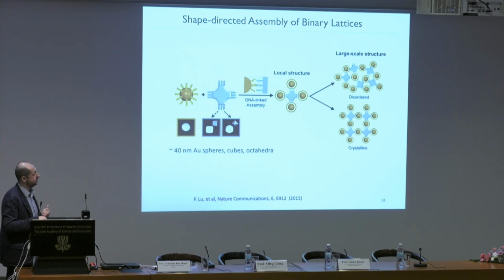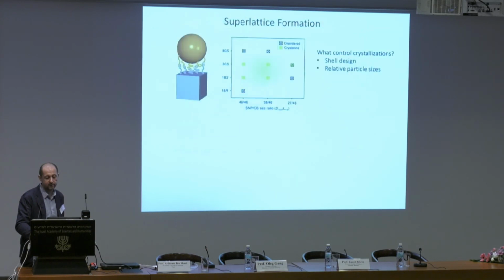So if you look at this from the local environment, this block essentially allows to coordinate particles according to the symmetry of the block. The hypothesis underlying here is that this can propagate, and the crystal structure can form, and the symmetry of the crystal structure will be related to the geometry of this block. Of course, it's not given that the structure will be crystalline. It may also be a disorder, and that's something which we started to investigate at that time, trying to understand what parameter really controls crystallization.